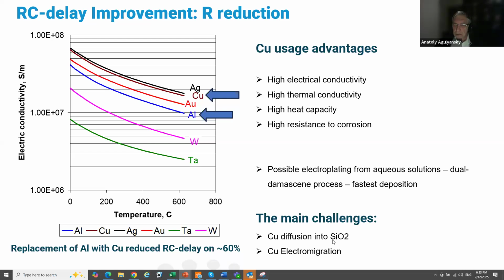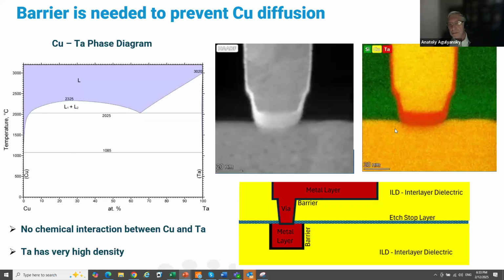Copper diffuses into silicon, and there is electromigration. In order to prevent diffusion, we use a barrier, tantalum. This is copper, this is tantalum, this is silicon oxide. And this is silicon oxide, the copper, and tantalum. Tantalum is a barrier because, as you see on this phase diagram, copper and tantalum don't like one another at all. Even in molten conditions, they are separated into two different liquids. Another point is the very high density of tantalum, 16.6. So it prevents copper from diffusing into silicon oxide. Solving this is not easy.